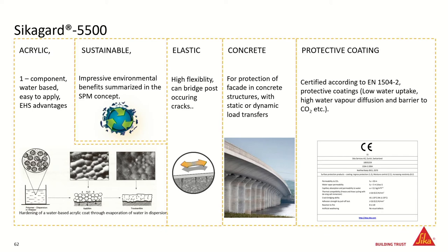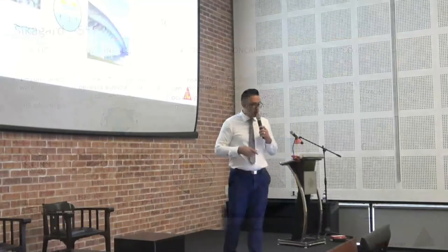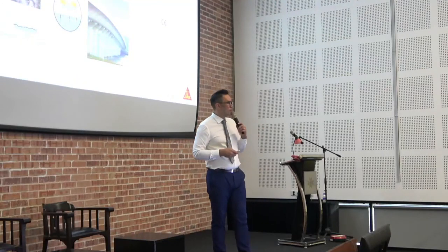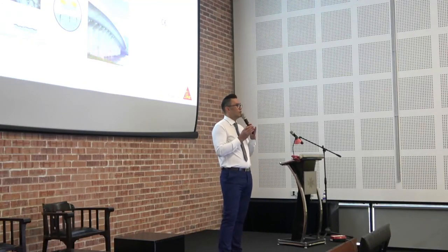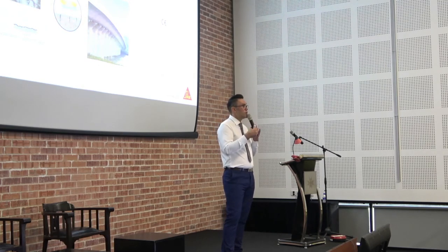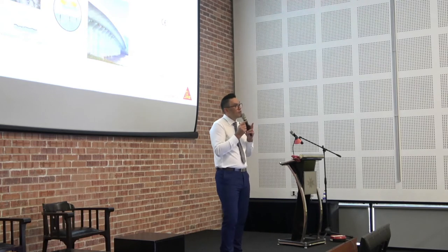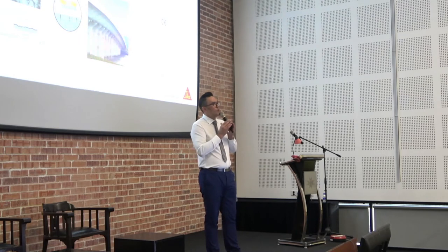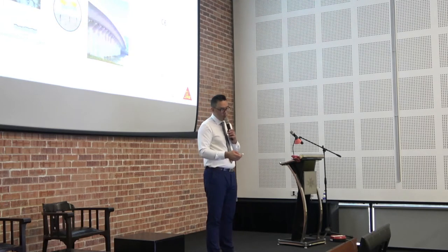And it's certified according to EN 1504 for low uptake and a barrier to CO2. So that means, depending on your concrete, we can actually measure the concrete cover equivalent based on the EN 1504 standard. If you need to increase the concrete cover equivalent, it's not replacing concrete. What it's doing is saying, as far as carbon dioxide penetration, it would be as if you had this much more concrete. So it doesn't change the structure. It just means that you can calculate how much more cover you should have.